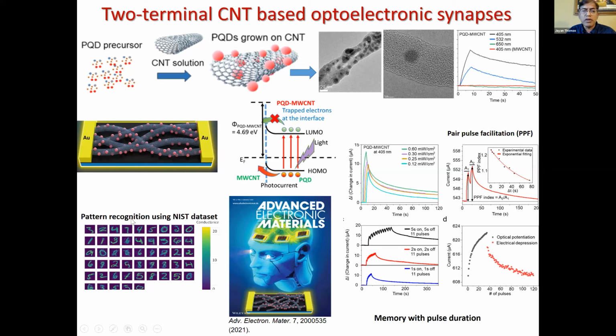Here is the pattern recognition using this type of device, and you can see all the properties, such as paired-pulse facilitation, the current from the second pulse to the first pulse, and all these plots show that it can work like a neuromorphic synapse. In this case we use optical potentiation. For the potentiation we use an optical signal, and for the depression we use an electrical signal.